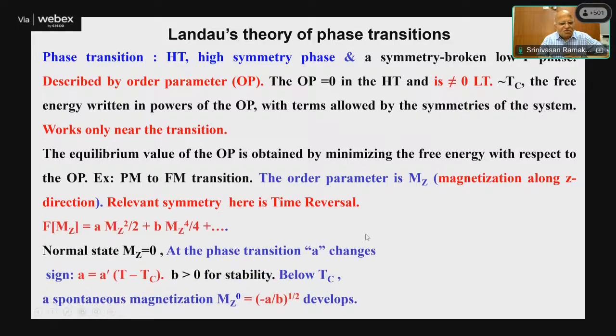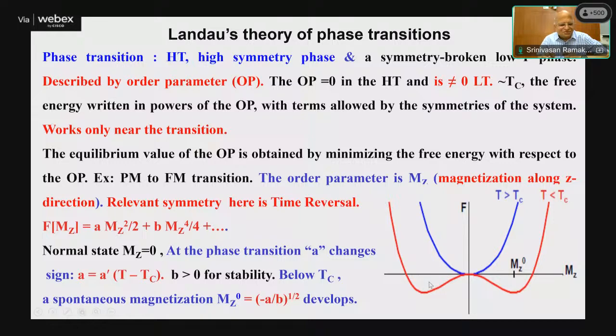Okay. So one can write the magnetization free energy of the system in terms of A mz squared by 2 plus B mz to the power of 4 by 4, and so on. In the normal state, there is no spontaneous magnetization. Below Tc, it will develop a spontaneous magnetization, with coefficient A given by this, and B greater than 0. The spontaneous magnetization develops when it goes from paramagnetism to ferromagnetism. How does the free energy change?